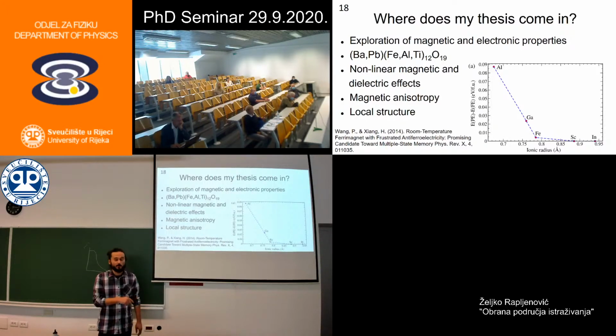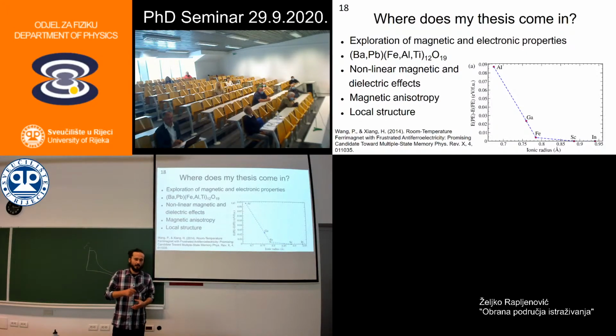So they calculated this with DFT. They said, okay, if iron is substituted by aluminum, how would it change the phonon dispersions? And they found that the aluminum had the greatest effect. They explained it because it's a small atom, it would have a larger tendency to go in this tetrahedral site and thus distort the structure. This is all I can tell.